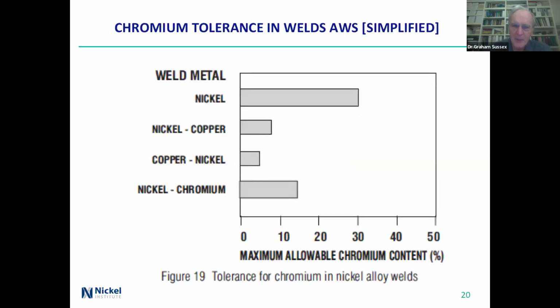This is from AWS, in multiple volumes, looking at weld metal and what you can have in terms of chromium. So if you're talking about nickel, then you can put 30% in. If you're talking nickel copper, then you're talking about 10%. If you're talking about copper nickel, then you're only talking about 5%. And nickel chromium alloys, and there are obviously some around, then you're looking at about 15%. This is just in terms of forming phases that are going to be detrimental to the actual microstructure.